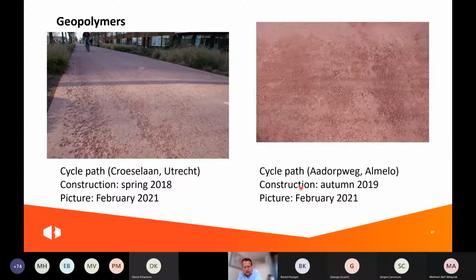Probably because it's not really a geopolymer with cross-linking between silicium and oxygen atoms, but it's mainly alkali activated slag, and then you still have a calcium silicium hydride, so CSH gel, but without a calcium buffer. And so I expect that the carbonation causes this damage. The carbonation, like with blast furnace slag cement with a high slag content, results in the formation of a porous silica gel.